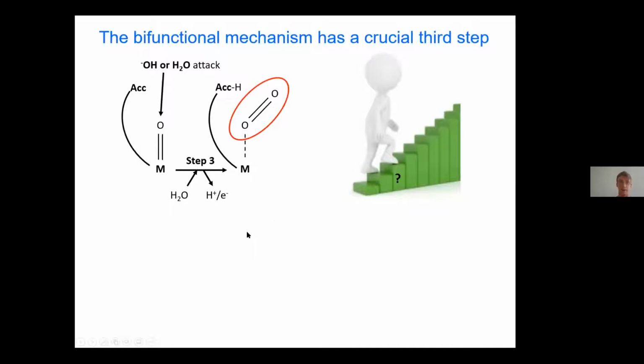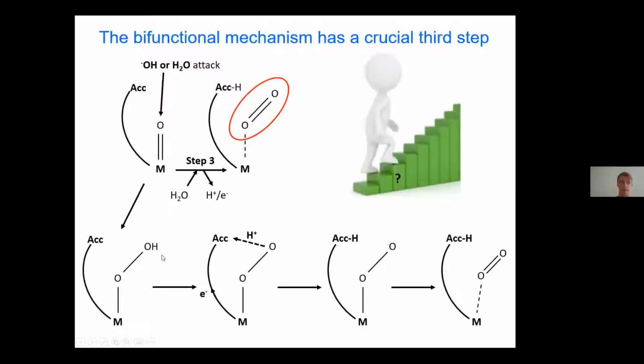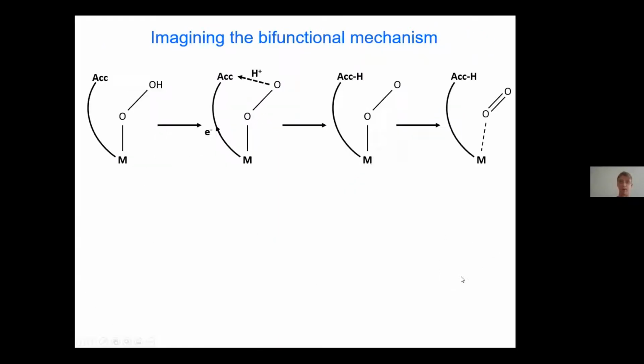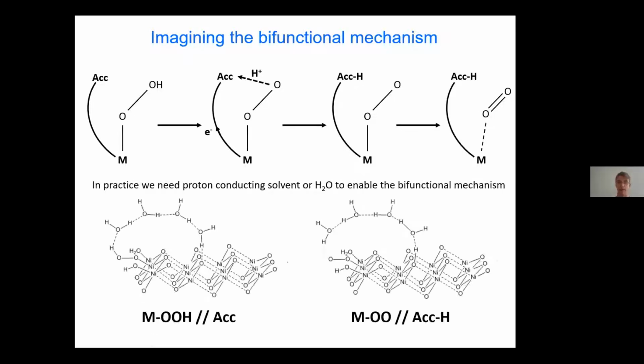So how can this reaction take place? We start from a water attack on the metal oxo. After that has happened, the proton moves from the oxygen to the acceptor, while the electron moves through the metal oxyhydroxide to the acceptor. And like this, we generate a hydrogenated acceptor site. So in reality, we need a solvent to catalyze this mechanism. So that can be very intuitively visualized like this.